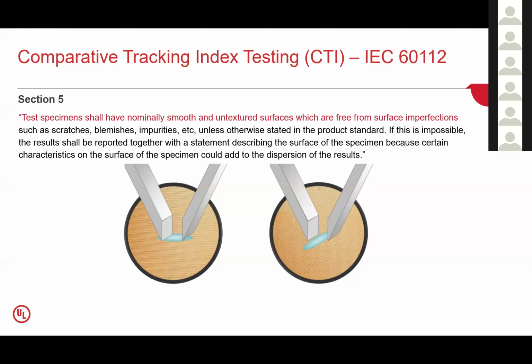If the tracks on our surface are oriented such that they line from one electrode to the other electrode, like on the image on the left, it could cause the liquid to wick between the electrodes and reduce the energy required to cause the tracking to occur. Conversely, if that surface detail parallels the face of our electrodes, like on the image on the right, it could cause the liquid to wick away from the electrode surfaces, leading to what appears to be a higher tracking index from that test. And we didn't even get into what happens if the liquid can wick vertically away from the surface, right? That can create yet another orientation aspect.